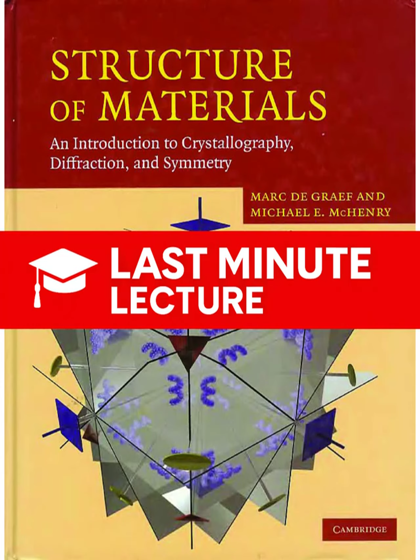It proves that cesium and chlorine occupy fixed, distinct sites. If this were a simple random alloy where the two atoms were just randomly distributed on a BCC lattice, you'd use an average atomic scattering factor. And in that case, the odd reflections would vanish completely, adhering strictly to the BCC extinction rule. So the fact that they appear at all, even weakly, tells us the material had long-range chemical order. That's the power of it. A tiny, weak peak confirms a massive structural fact. Chemical ordering over random distribution.